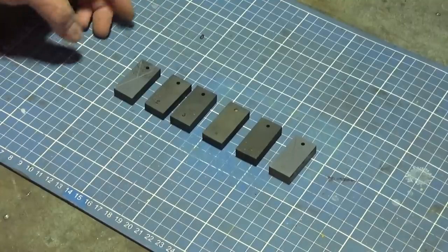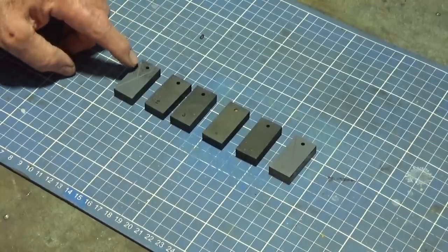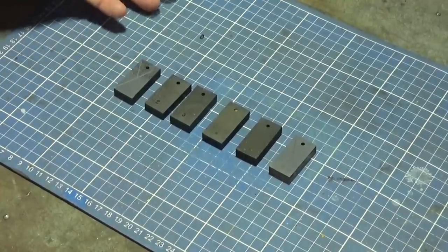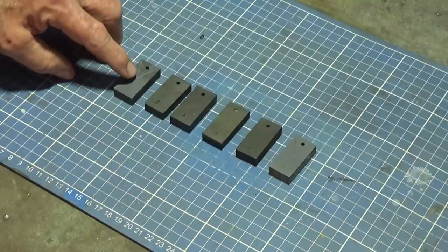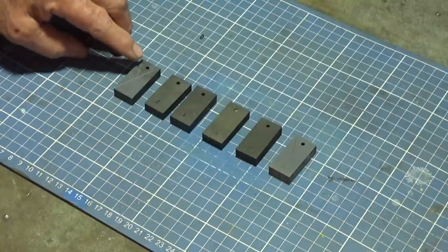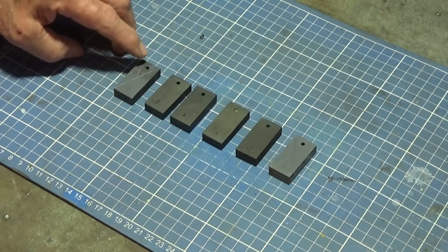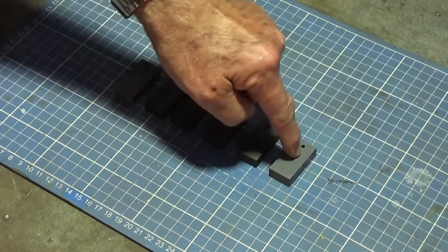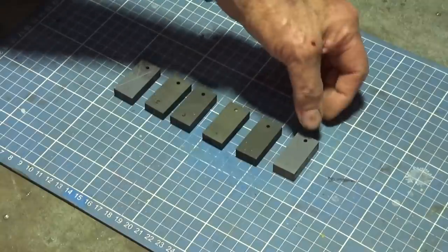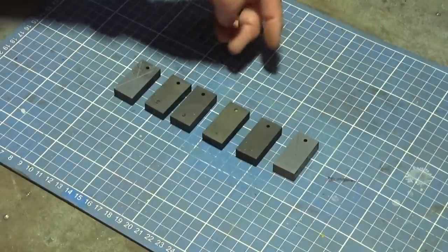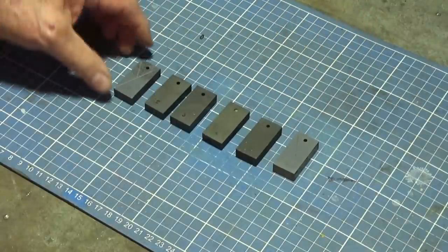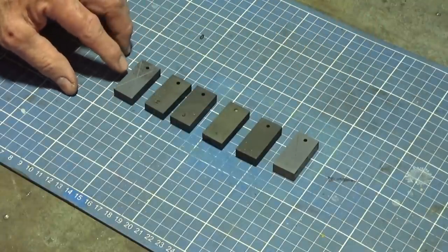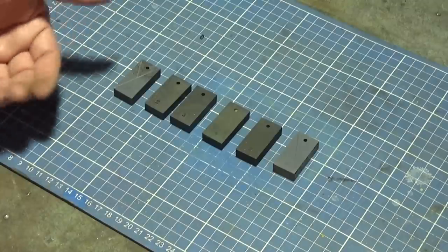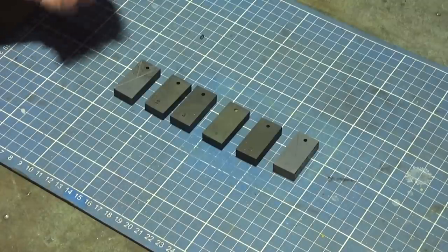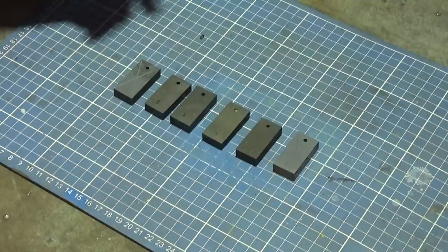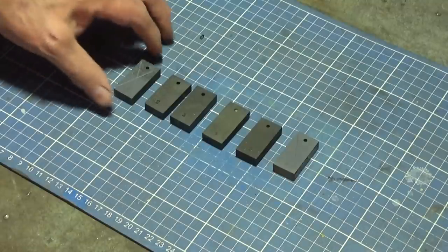So what are my conclusions? Well, firstly, the paint adhesion on the Parkerised finish didn't hold up as well as I thought it would. It hasn't completely delaminated, it's sort of pulled off in small patches. The bare steel one had the same sort of result, probably better than the Parkerised coating. Could be that I didn't rinse this Parkerising properly and there's some sort of film left on the surface which has stopped the paint from adhering. But hey, I'm just making excuses.